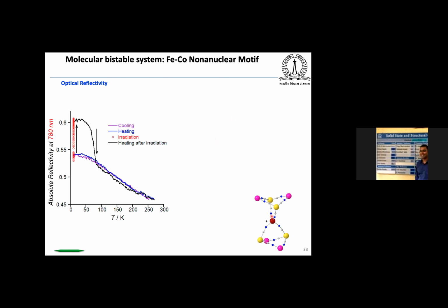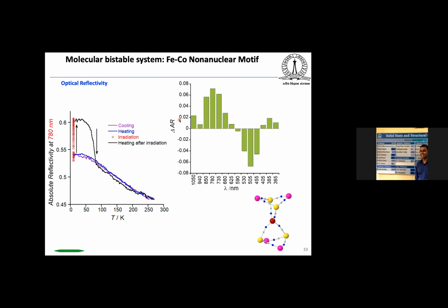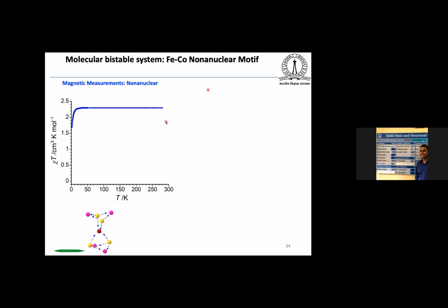And the metastable state is also relaxing back at approximately 60 Kelvin. You can see the system shows no thermo-induced metal to metal electron transfer near room temperature. And you can see that 780 nanometer light shows the maximum effect from the histogram plot. And when you measure the magnetic property from room temperature to low temperature, it shows only the signature of cobalt 2 high spin.